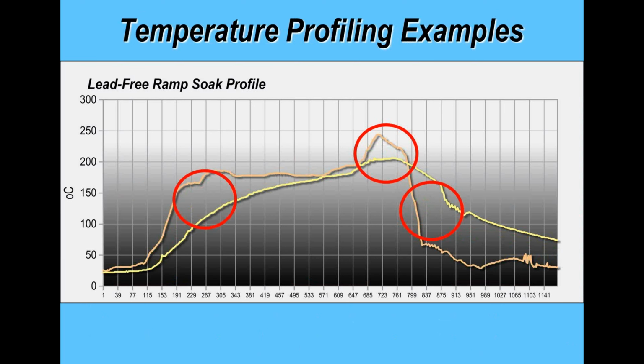So if we just strip away some of the profile information here, we've got this delta T. And there is no shortcut for trying to improve delta T. It's all about experimentation with your profiling system and experimentation on speed of throughput, peak temperatures, and peak temperatures in different zones. And at some point there is a limit to what you can do with your machine and your product at the speed you want to run it. So again, it's finding those sweet spots. And there are no tricks to this, it's a case of experimentation.